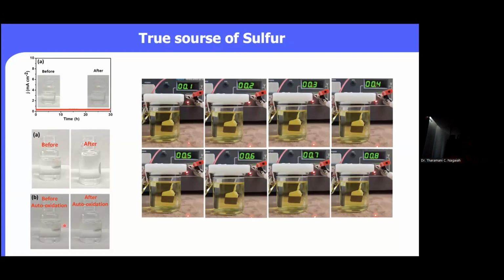Again, another approach, we have done the auto-oxidation. Even when we kept the solution for 1 week to 10 days, we did not see any precipitation. This confirms that whatever sulfur or polysulfide is produced is due to the H2S, and that means the electrocatalysis of H2S, not by our catalyst.